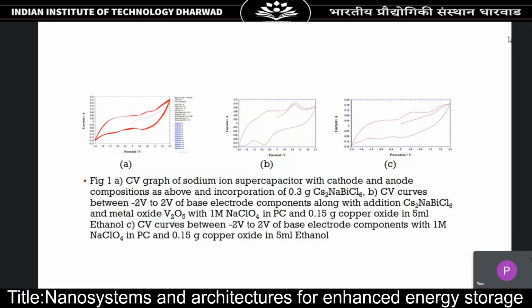So these are the CV graphs, the first one is for the base material. We have used the perovskite material as the nano component in the cathode, which is nothing but cesium sodium bismuth chloride. And B and C show the behavior when we add copper oxide nanofluid.